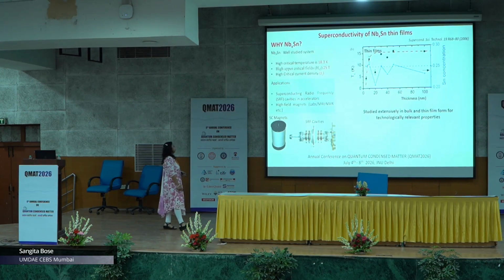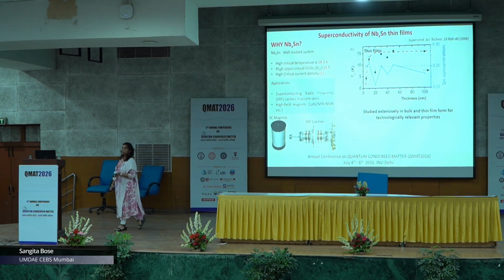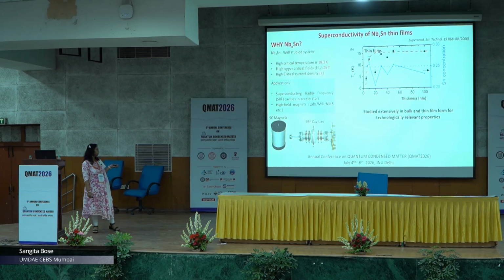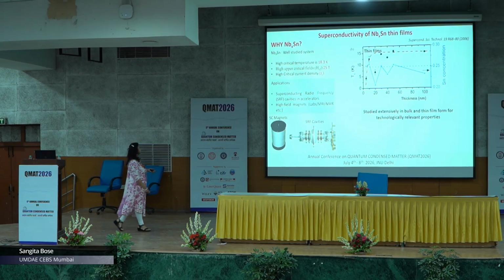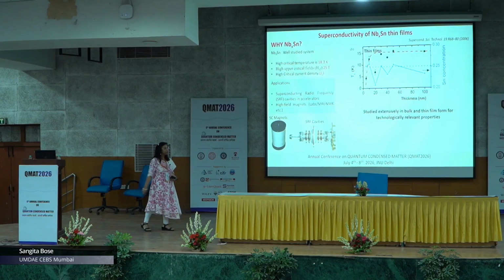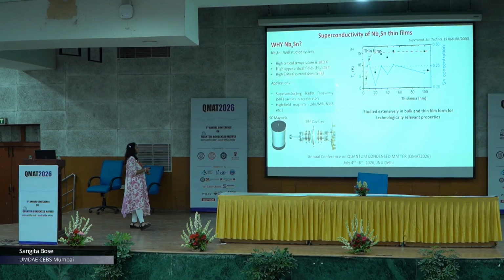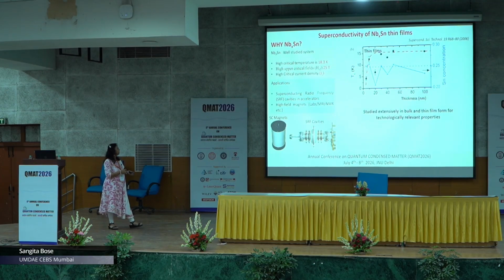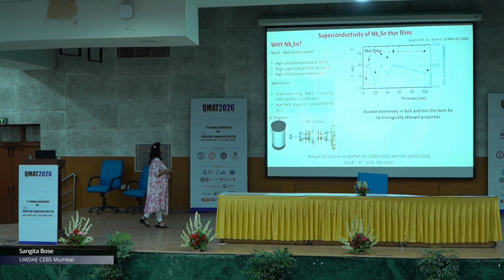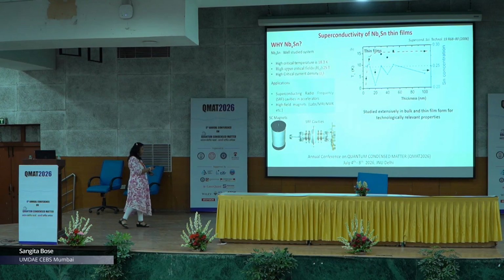So, what we did is that we were trying to probe this in a system of niobium tin. This is a very old known superconductor, and you might think, why are we studying this? Of course, this has been studied mainly for technologically relevant quantities, and we do thin films. So, we will be growing thin films. If you look at the variation which is known, the variation of the superconducting transition temperature in these systems, as you change the thickness, the x-axis is thickness and y is Tc. So, the Tc is known to decrease with the thickness.